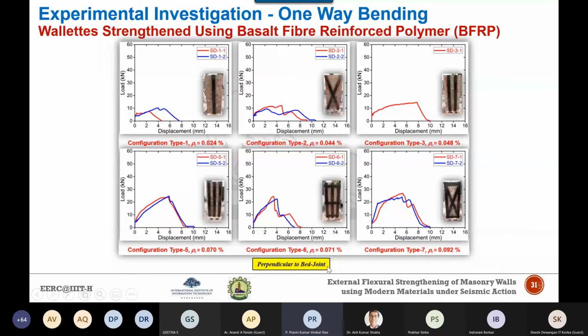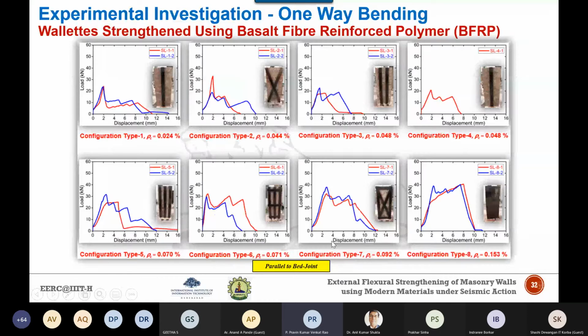Here you can see that the strength enhancement initially was 10 when you applied a 0.024 percentage of reinforcement, which is very small. Now, with increase in reinforcement ratio, you can see that the strength is also increasing. A similar trend you can also follow for the parallel to bed joint. Here the strength enhancement is around 24. Now when the reinforcement ratio is increased from 0.024 to 0.153 percentage, the maximum strength gained is almost near to